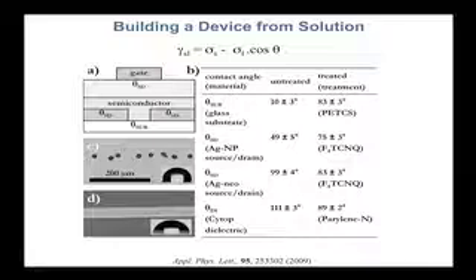The contact angle of the glass is about 10 degrees. And then there are two silvers here that I am giving as an example. Once you figure out how to print the silver and you measure their water contact angle, one is around 50 degrees, one is around 100 degrees. So if you made a TFT like this, when you come to print the semiconductor, it is going to see 10 degrees at this interface and 50 or 100 degrees at the contact. So obviously the semiconductor will only wet the channel and will de-wet from the electrodes.